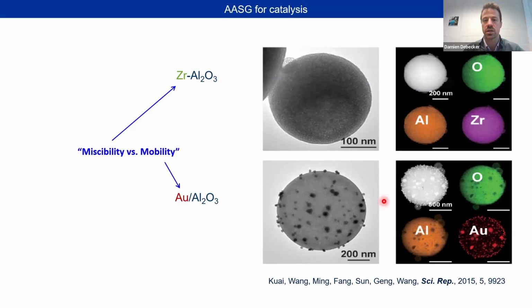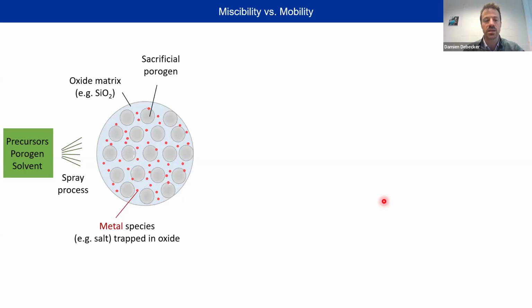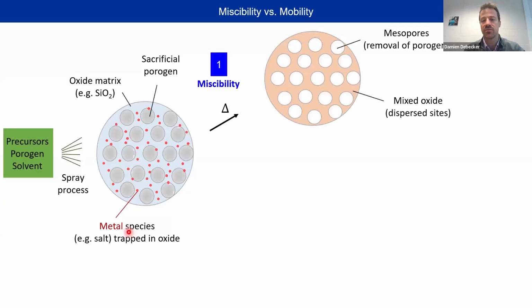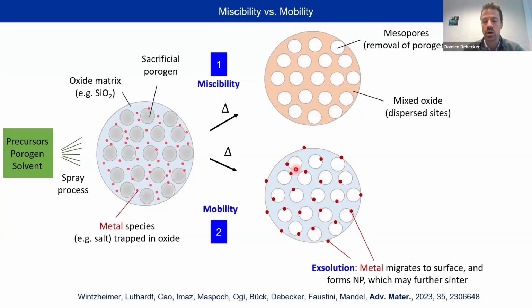So these are two scenarios that I want to discuss today. And I have illustrated it again here in this schematic. You spray your materials, you get your particles with dispersed metal species because of the kinetic quenching. And then either you have miscibility, so you will form a mixed oxide with pores, right? Or you have the mobility scenario where the metal precursor that is here will just migrate towards the surface and form metal nanoparticles. So this exsolution is quite nice because it allows you to bring the material towards the surface and to form nanoparticles you need in catalysis.